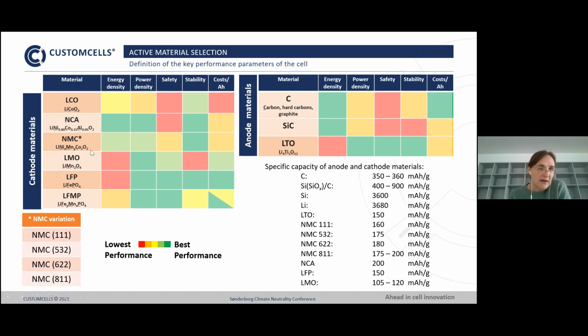First, it is more stabilized, for example, than the LCO. The expensive cobalt is diluted with cheaper materials like manganese and nickel. And furthermore, nickel has, in comparison to other materials, a high specific capacity. So the amount of lithium ions that are able to be provided per gram, which is in batteries shown as milliampere hours per gram, increases the more the nickel content increases, which is shown by these numbers here. The NMC 111 would be 33% nickel, 33% manganese, 33% cobalt. We are now even beyond 80% of nickel, more in the region of 90% nickel, because there we find higher specific capacities, which means less material for the same amount of energy.